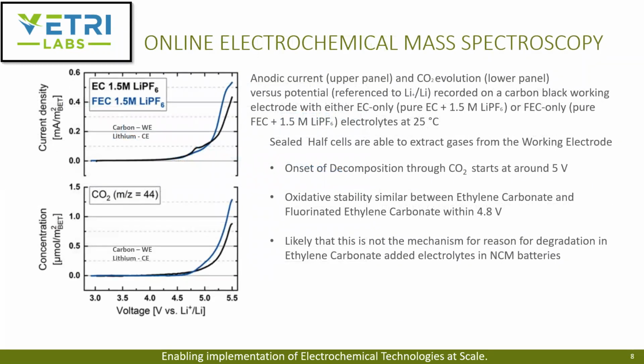They further did online electrochemical mass spectroscopy, studying the carbon dioxide evolution, wanting to make sure it only came from the electrolyte. So they used a carbon black working electrode and studied the interaction between the ethylene carbonate and fluorinated ethylene carbonate, using sealed half cells so they could extract gases from one side of the working electrode. They saw the onset of decomposition for CO2 starts at around 5 volts, or significantly takes about 5 volts.